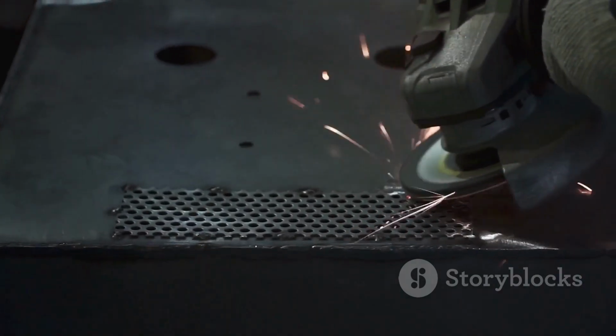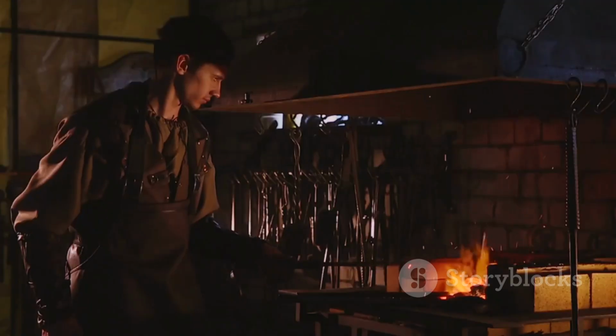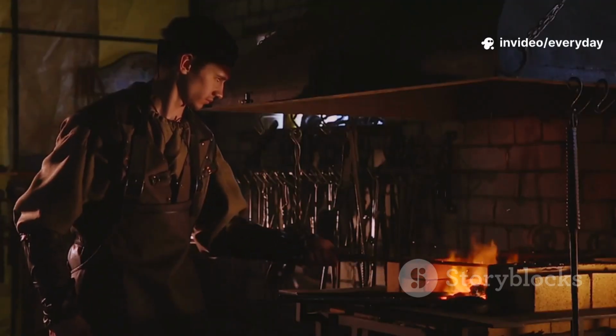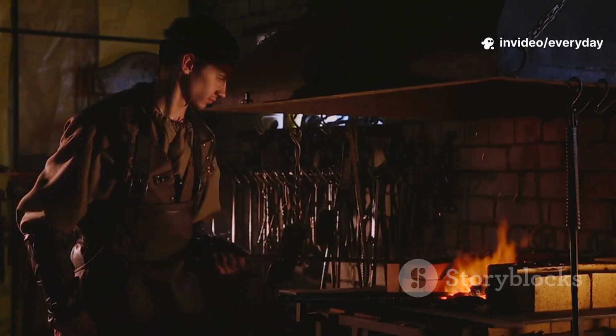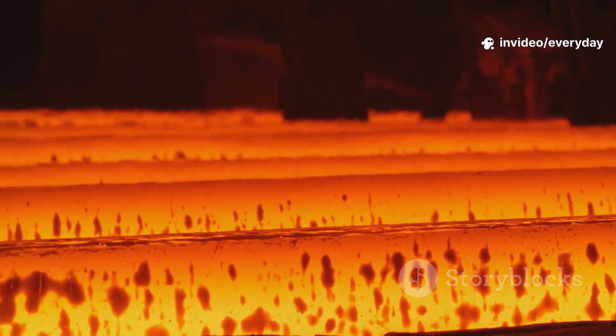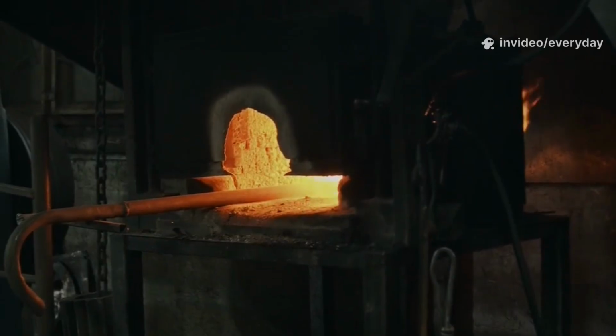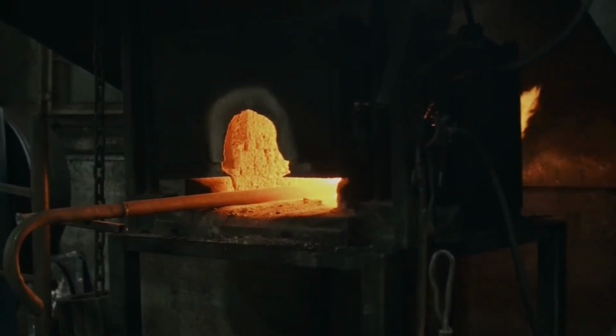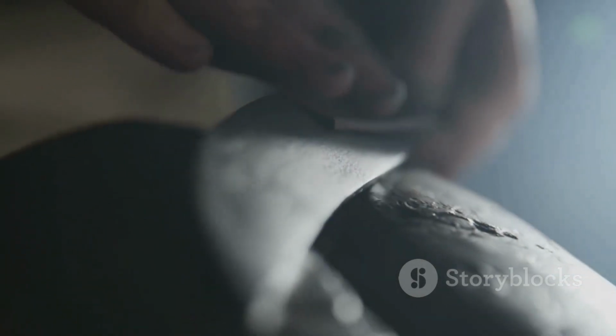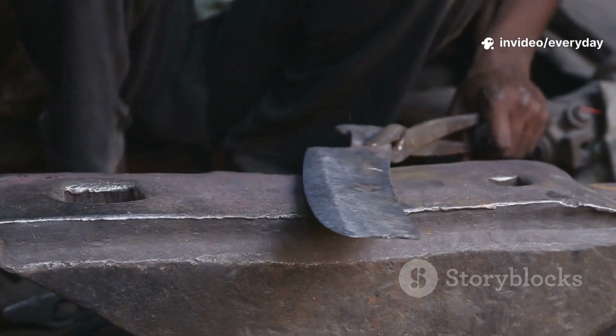All mating surfaces must be impeccably clean. Adding San Mai mid-process? Stop, re-clean, and assemble anew. Dirty cores guarantee delamination and failure. Heat all three layers evenly and set every seam carefully. Ground and etched, San Mai reveals beautiful lines and serious performance. Pull it off and you prove skill and control.